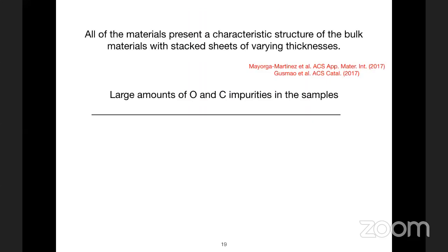After finding this, we looked at the experimental papers more closely, and what we found was a statement from these papers that all of the materials present a characteristic structure of the bulk materials with stacked sheets of varying thickness. Now, when you have stacked sheets of varying thicknesses, you of course have edges exposed. And they also show that there are large amounts of oxygen and carbon impurities in the sample. We haven't as yet addressed the question of impurities.